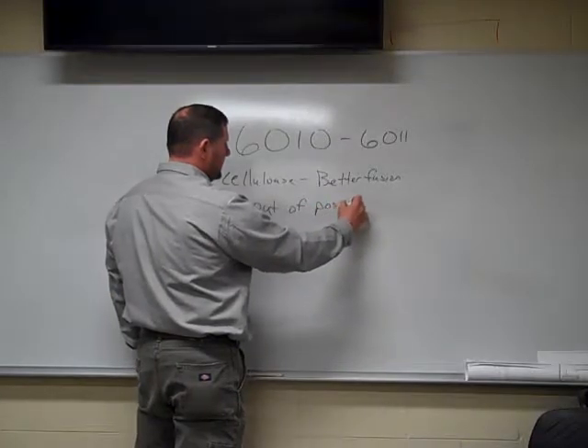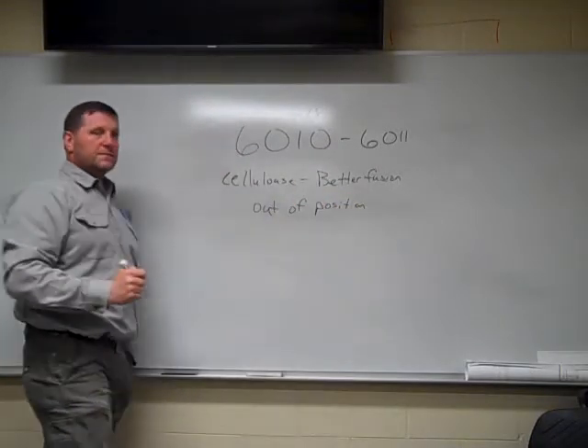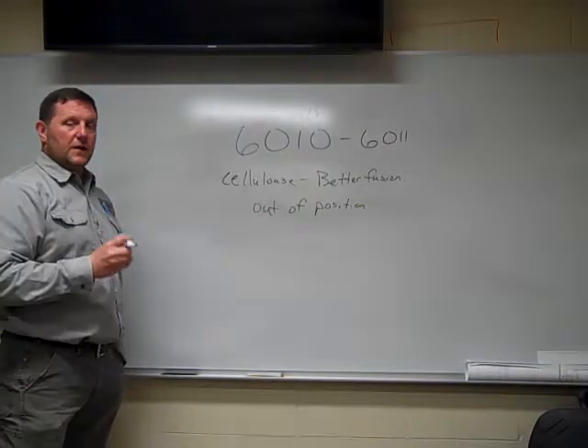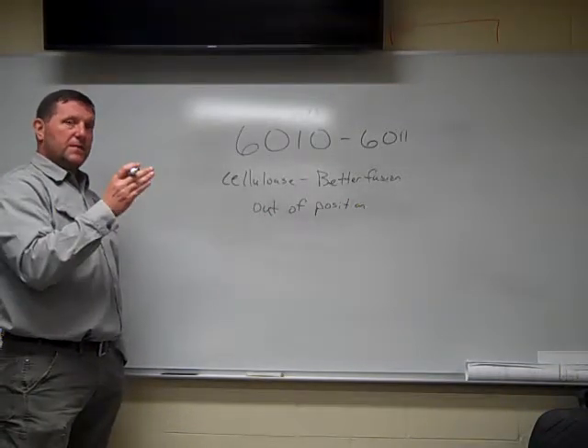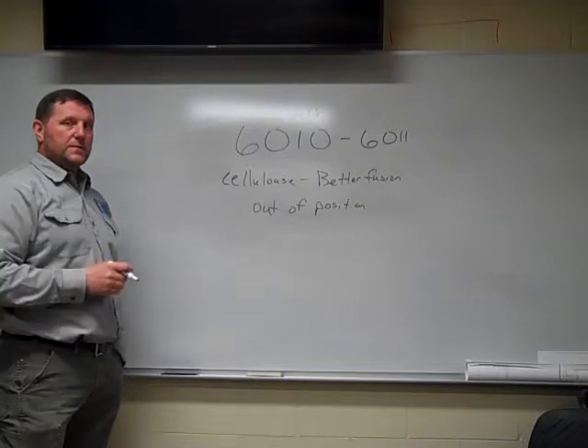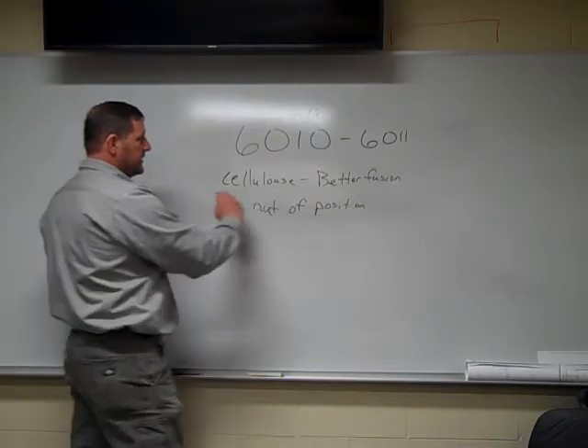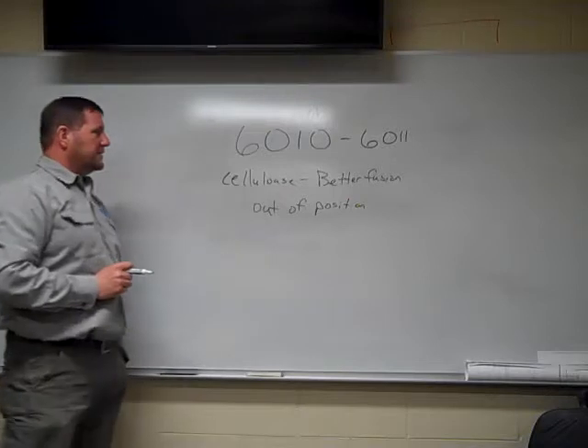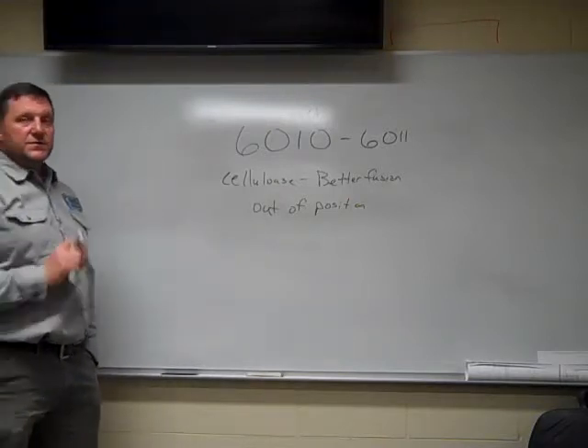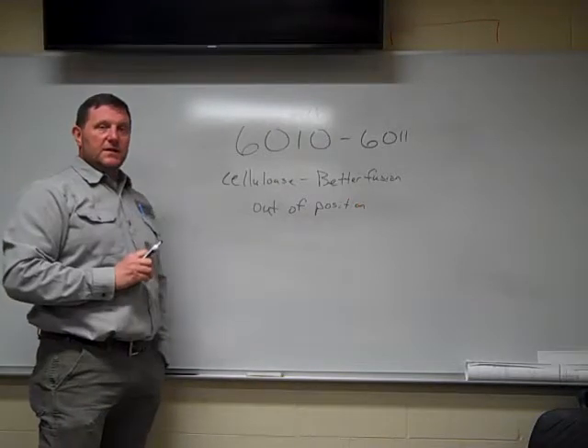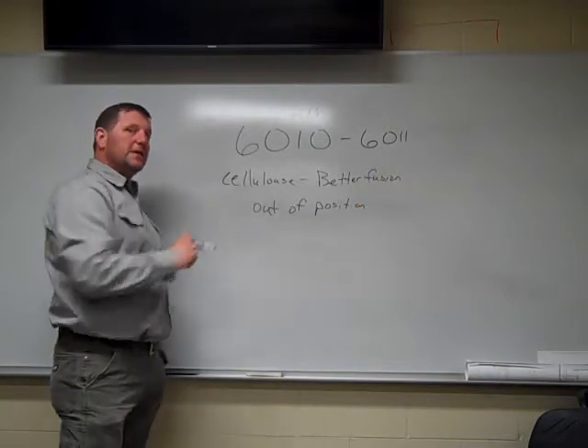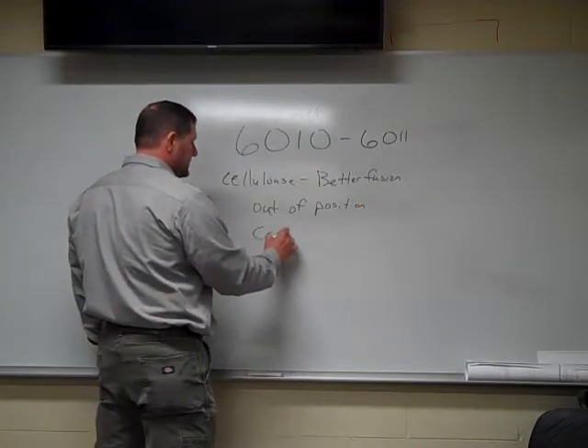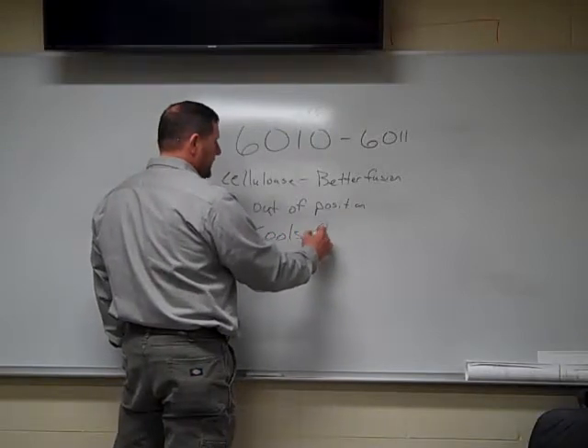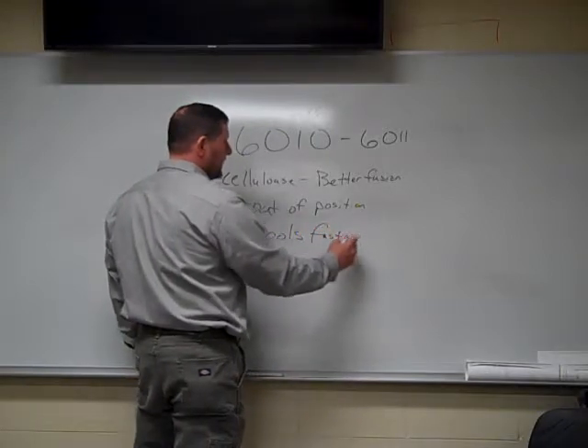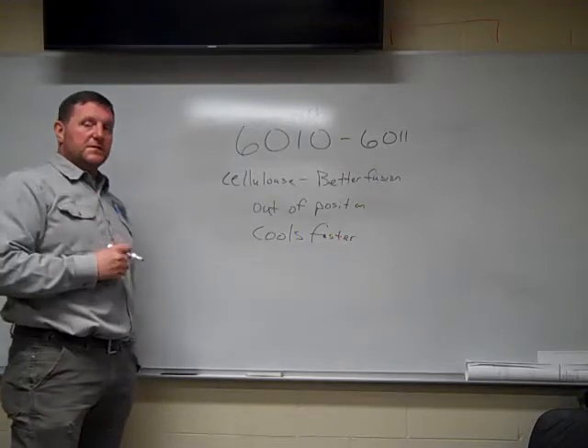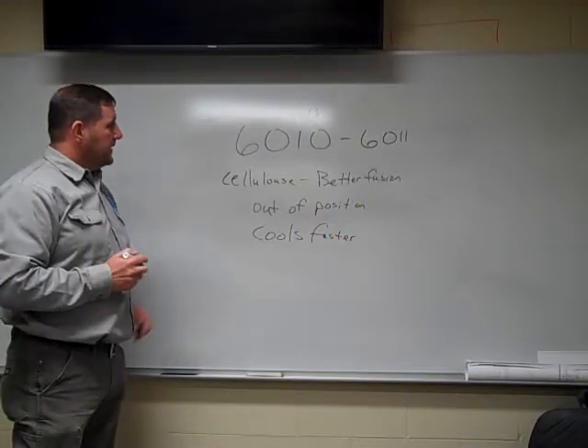Why do you think they'd be good for welding out of position? Because we have less flux. It means we can control our arc better as we're welding vertical up. We have less stuff to control. So 6010, cellulose-based flux, you can see a huge difference when you switch from 6010 to 7018. It's not a very fluid puddle. It cools a lot faster. That's probably one of the main reasons we weld out of position with them, and you do your root passes with them. They cool fast, so keep that in mind.